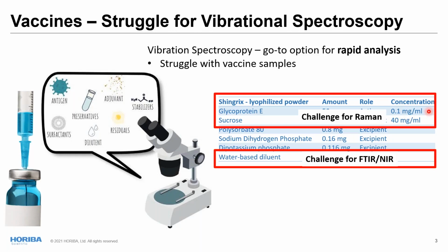That's quite low for vibrational spectroscopy. And then to make matters worse, we have sucrose here at about 400 times. And we know for certain that for Raman, the sucrose is really just going to overwhelm the protein signature. And oftentimes, for vaccine characterization, the protein signature is what is important. And then we go down to the water-based diluent, and that will be a challenge for FTIR and near infrared. So right now, with our standard tools, we're finding some challenges.